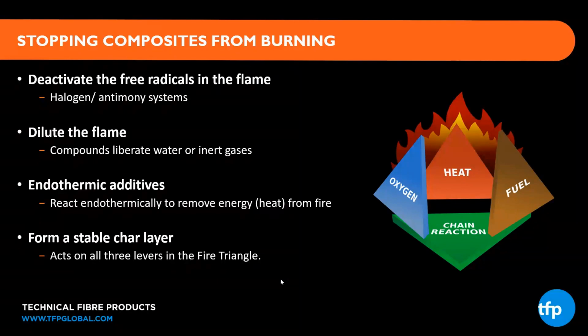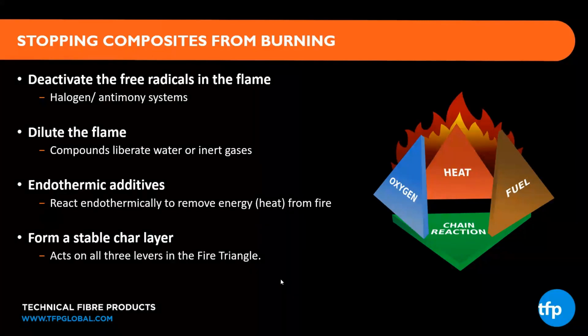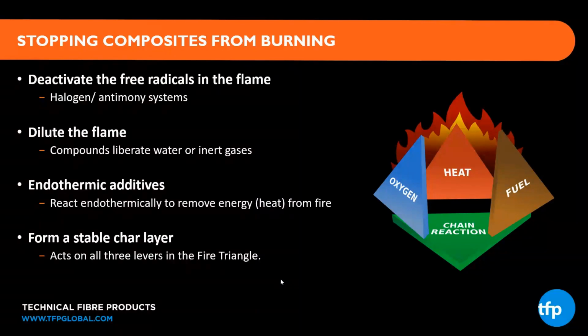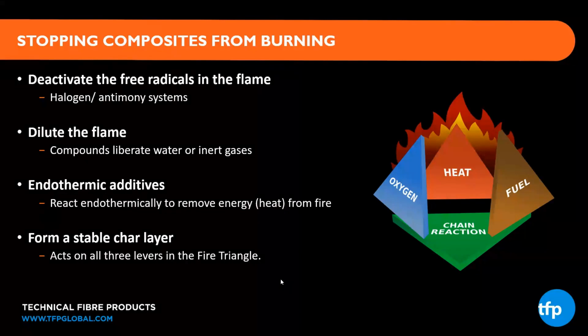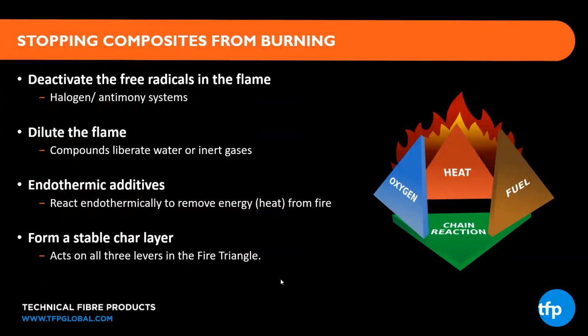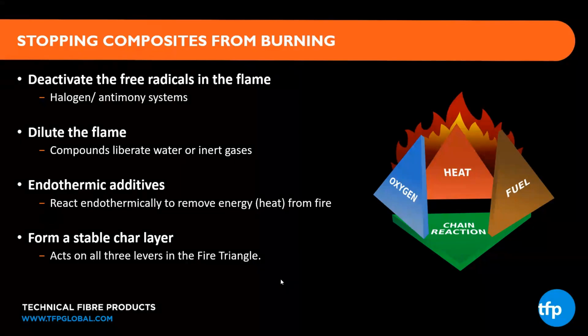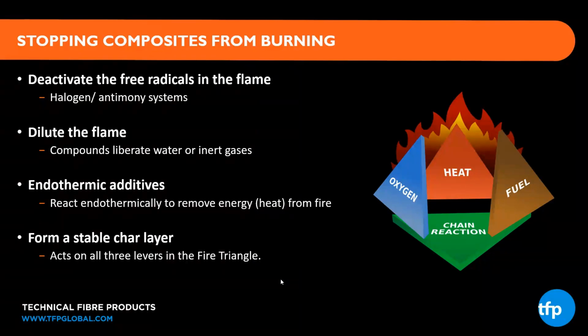and that's to incorporate technologies or products that form a stable char layer on the surface of the composite during the fire event. So this could be an intumescent paint coating, a gel coat, or an intumescent veil. So under the action of heat, these products intumesce or swell, expand to form a stable char layer, often a carboniferous char layer, that effectively insulates the backing laminate and protects it from the fire.